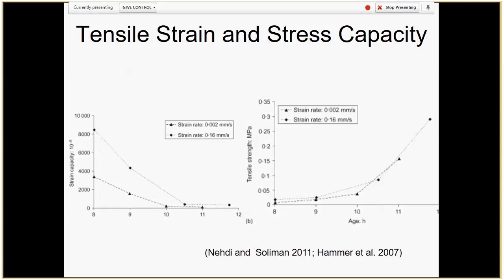Even after dealing with this data for quite a while, I can't understand completely why section 124 is not damaged, but that's the case. One of the explanations I found is in a paper by Hammer et al., and later discussed by Nehdi and Soliman. Basically it says that at very early age, the concrete has very high strain capacity, so it can withstand significant strains, because stiffness is low, tensile stresses are low and tensile strength is low. But with time, stiffness increases, so strain capacity decreases while strength increases. So basically there are two factors fighting with each other.